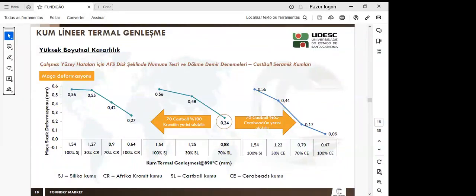They used a specimen to test and validate this behavior. With 70% of Castball, the core deformation result is very similar to 100% chromite. We can use another composition and have a cost reduction, and can replace 65% of mullite and maintain the same dimension results.